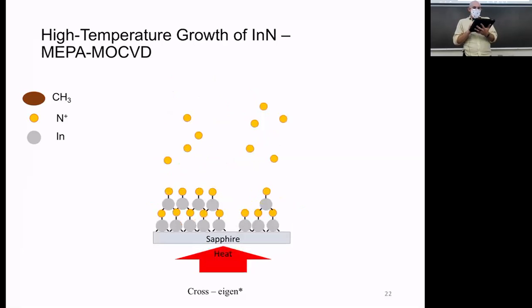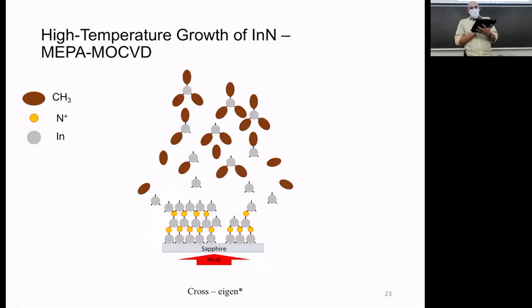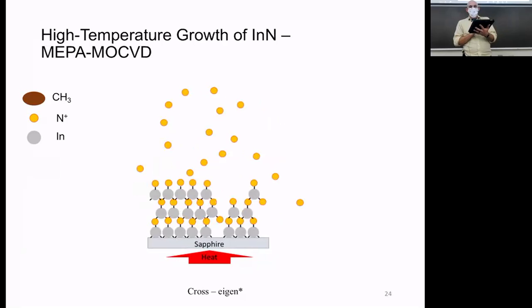So as we move forward, in order to grow indium nitride, we then get the indium split apart from its methyl groups, and we can then deposit nitrogen directly onto it. So as we grow these structures by layer, we can put down some indium. We then deposit nitrogen with the plasma. Then we can put down another layer of indium, and we can put down another layer of nitrogen ions. So that's exactly what we do. We deposit a little bit of nitrogen. We then let the methyl groups dissipate, and we then expose it to plasma.